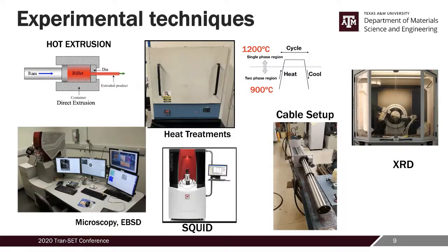And throughout our experiments, we use different experimental techniques. We use hot extrusion, we use microscopy or EBSD to look at the grain orientation. We use furnaces to do our heat treatments. To measure the magnetization change, we used a SQUID. And here is the cable setup that we built with my undergrads in our lab to fabricate the iron-based SMA cables. And again, XRD for texture measurements.